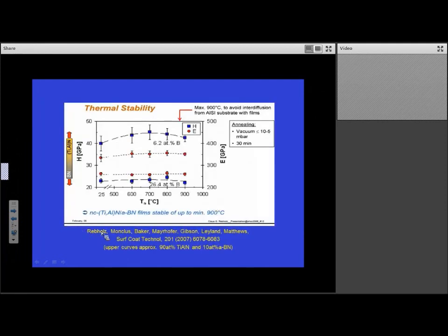So this is some work that Klaus Rebholz did and has continued to do. I wanted to mention this because many people will say, what's the point of having a metallic nanocomposite because it won't be temperature stable. But actually, we've proved that some of these metallic nanocomposites are remarkably temperature stable. This is some work showing the hardness and the elasticity stability even up at 900. And that work was stopped at 900 because of the risk of getting into diffusion with the steel substrate.